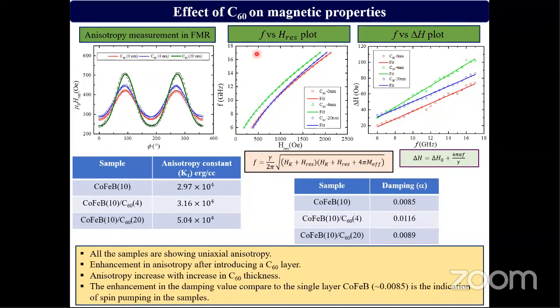So this is the frequency dependent FMR plot. This is F versus H resonance, and this is delta H versus F. We have fitted these 2 plots, and from the fitting we have evaluated the damping constant, and we have seen that for the cobalt iron boron 10 nanometer the damping is low, 0.0085. However, when we introduce a C60 layer, the damping is enhanced. So this enhancement in the damping is also an indication of the spin pumping happening in the samples.